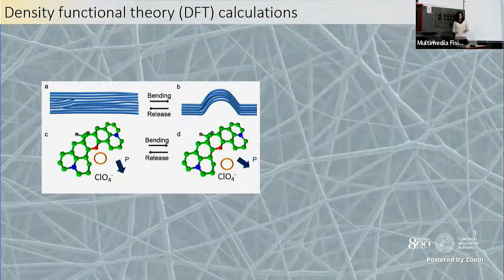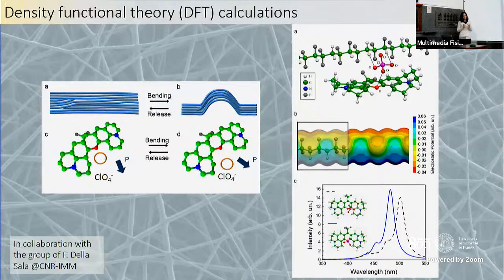Through density functional theory, in collaboration with Fabio Della Sala, we tried to rationalize this behavior. And here the point is that we have three systems at the molecular scale. We have the piezo polymer, and we have the organic dye. The organic dye has a counterion inside, and this counterion interacts with the dye, so with the molecular dye, and with the piezo polymer. And when a stress is applied, you change the interdistance between the counterion and the piezo chain. What we got was that the counterion is going to interact with the positive tail of the polymer, which are H atoms, and create